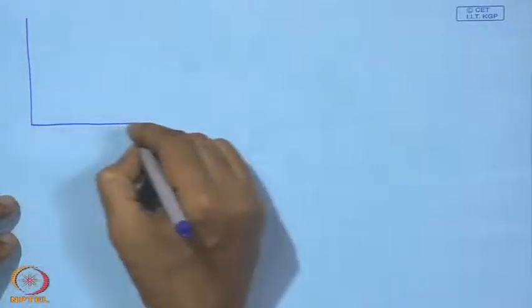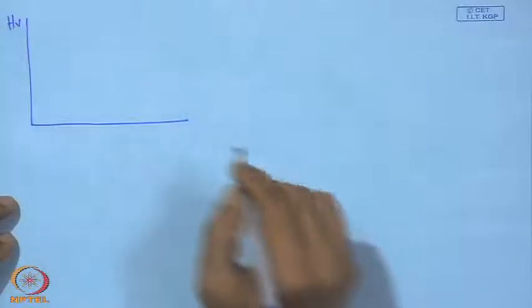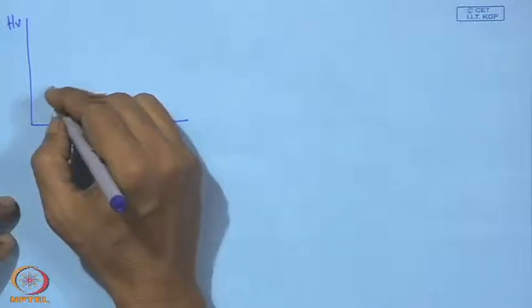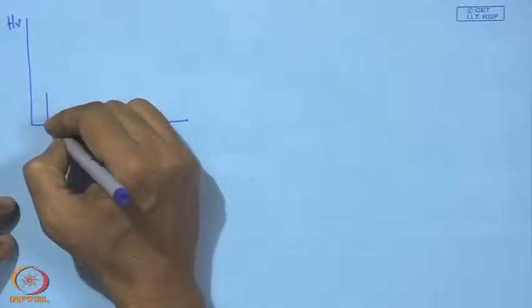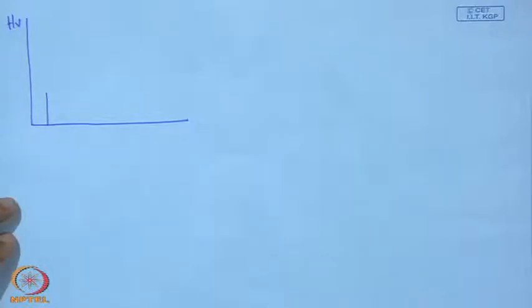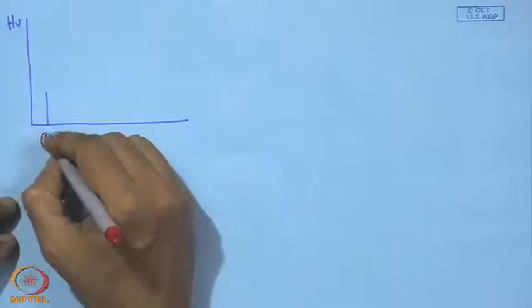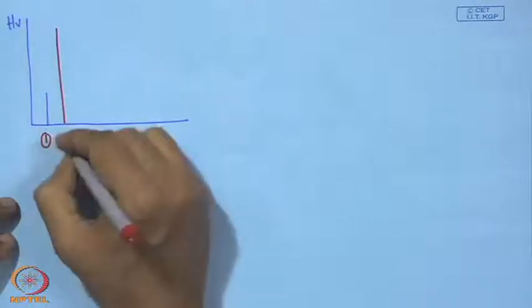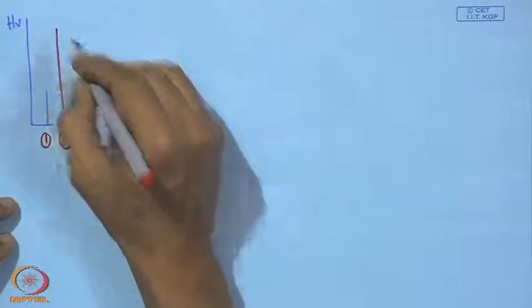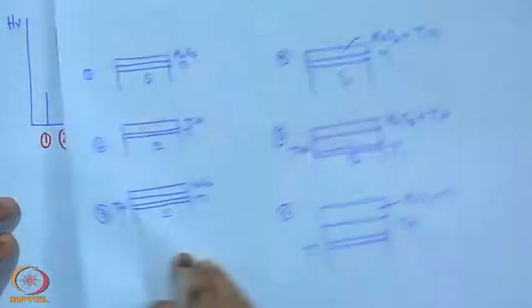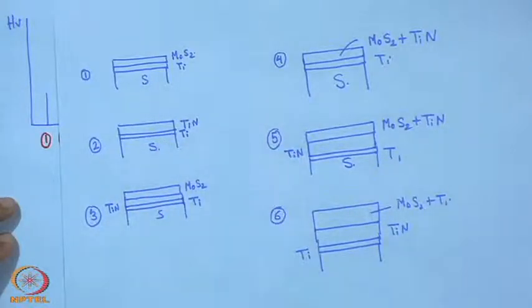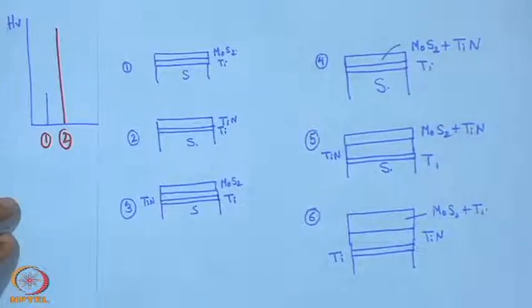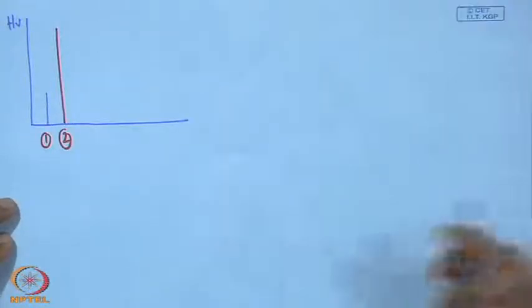Now, when we have such architecture, we can find out here, that means first of all this is hardness, this is HV, and on this HV we can have a hardness something like this, and then we can have this is number 1, and then number 2 will be very high for obvious reason, because number 2 means here we just have titanium nitride, and since titanium nitride is known for its hardness, we expect a higher hardness